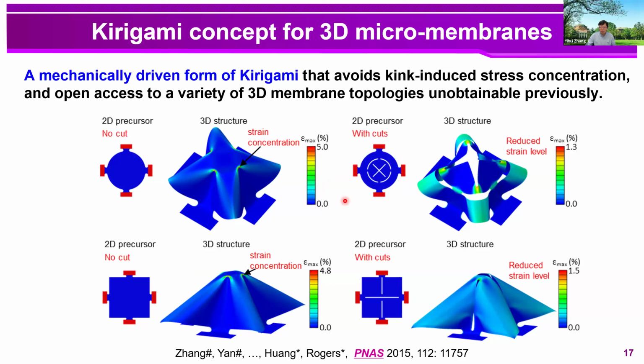To resolve this issue, we introduced kirigami designs to change the load transfer paths within the structure. And after introducing kirigami cuts, the localized deformations disappear, and the strain concentration is evidently relieved. This is evidenced by the value of peak strain. In these 2 examples, the strain reduces from around 5% to 1.3% and 1.5% respectively. And in this case, if you use single crystal silicon to fabricate, they will survive.